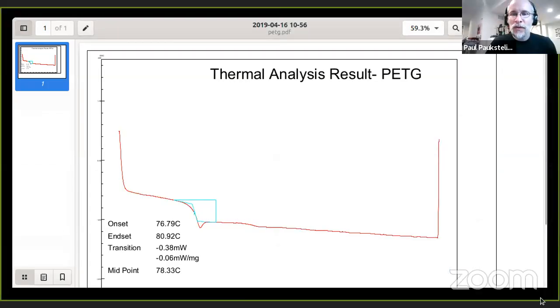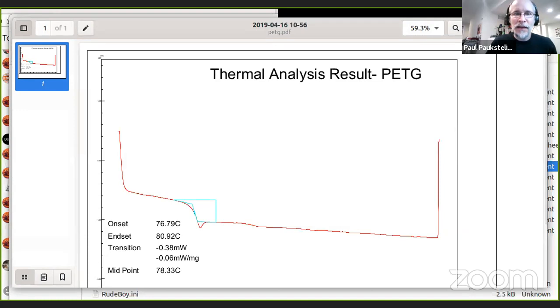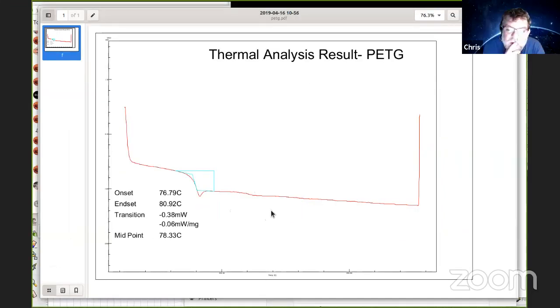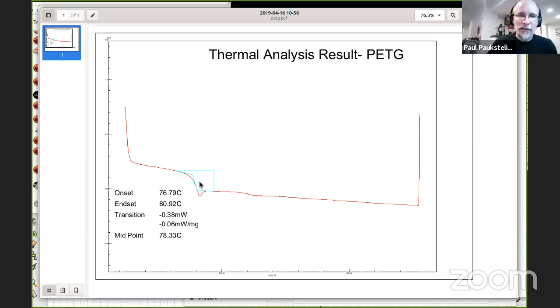And I just want to point this out. This is the difference that you see between PLA and PETG. Notice in this case with PETG, this is the glass transition temperature, which is around 80 degrees here. But the steep melting curve that you get with PLA is not there. So this is an amorphous solid, which is why you don't get a distinct melting curve, whereas with PLA, because it's actually crystalline, you see this big change when it melts.